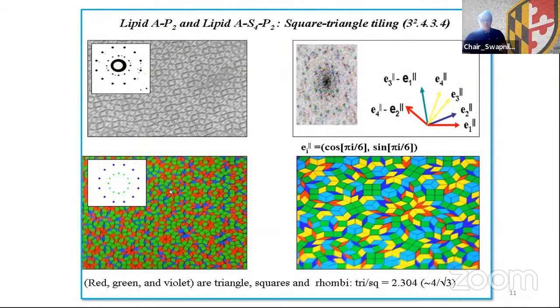Quasi-crystalline structures exhibit a non-crystallographic packing of non-identical lipid A diphosphate spheres. The spatial packing was in either a cubo-octahedron or an icosahedron. It was noted that the observed 3.3.4.3.4 tiling was a crystalline analog of the icosahedral quasicrystal. The tiling pattern of the triangles and squares possesses a P4GM plane group. Another coded lipid A diphosphate approximant showed an 8:3 ratio with 6-fold symmetry and plane group P6MM. Both dodecagonal phases revealed a ratio of approximately 2.304.